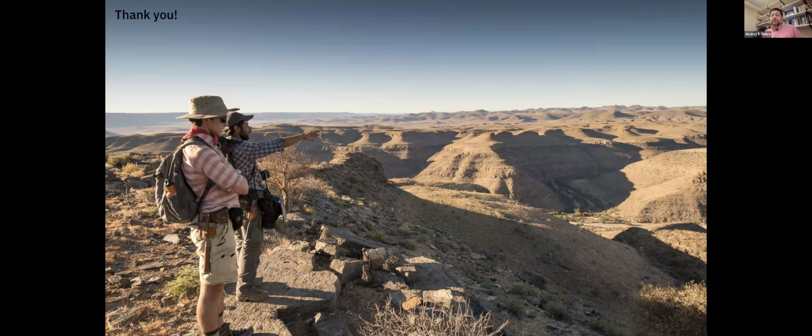That said, there are probably some really easy, basic rules to go by. If the density of all the features in that sample is similar, for example in the case of granites, you're probably going to struggle to do that 3D reconstruction with X-ray CT unless you're using really interesting phase shift methods. A lot of the fossils I look at are carbonate in carbonate, so everything's been replaced. You look at a thin section, it's all calcite that's been replaced. It's probably going to be really hard to get a three-dimensional form from X-ray CT. Not impossible, but it's probably a good indicator that you might end up going with the destructive method.